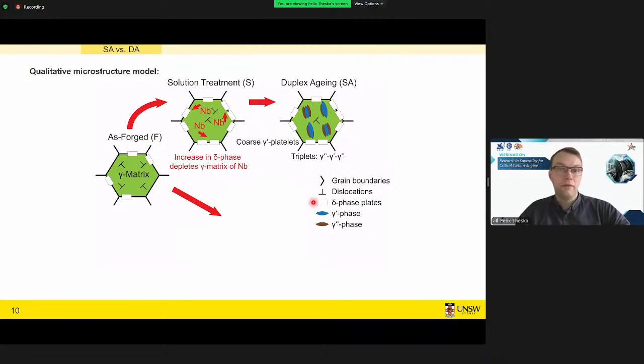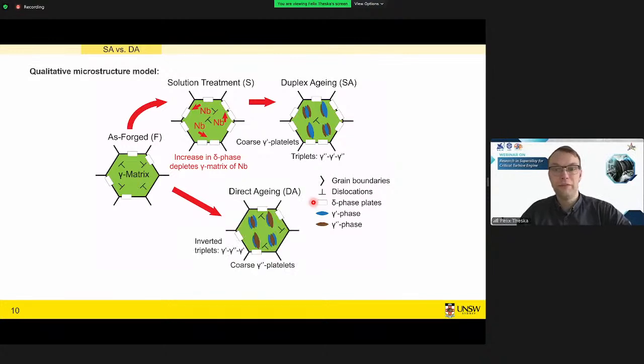On the other hand, during direct aging, we retain the high dislocation density and a lot of niobium in the matrix, which favors the gamma double prime precipitation. So we find this phase as the center particle or the larger particles. Okay, if we combine this together with the smaller grain size, a higher dislocation density, more niobium in solid solution, plus these changed co-precipitates, we find there are contributions to this increased yield strength from all 4 factors.